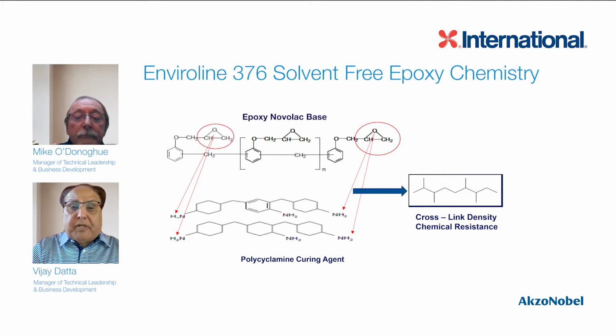Now, talking about the polycyclamine curing agent and the Novolac epoxy resin, as a formulator, when we formulate these coatings, we want to make sure there's a minimum free volume. Why do we want the free volume to be so little? Because it will not have penetration from the water and other cargoes. But when we raise the temperature, this free volume can increase if the coating is not formulated properly. So our goal here is to keep the free volume low even at higher temperature. This is achieved by using proprietary fillers, additives, and also controlling the stoichiometric ratio between epoxy and the curing agent.